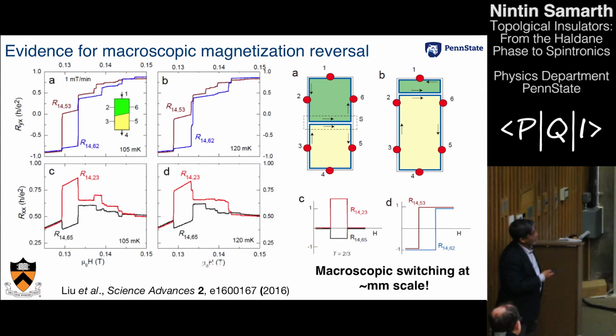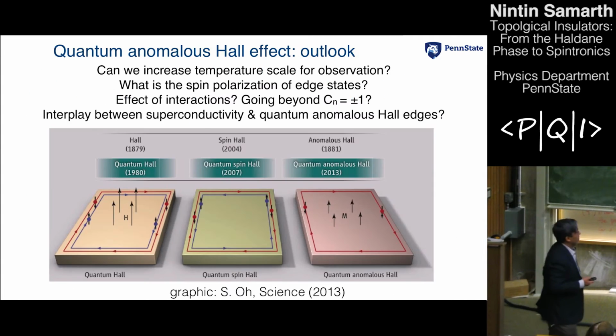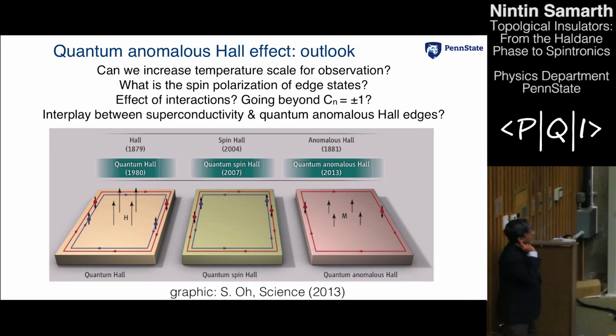So indeed, if we assume a simple model like this, not of uncorrelated switching of little magnetic bubbles, but rather a macroscopic change of the magnetization across this large millimeter scale sample with a single domain wall, or at least some simple structured domain wall, sweeping by, we can in fact reproduce this kind of phenomena that we see in experiments. In other words, Rxx jumps up and down for opposite contacts, and Rxy has a lag in the field at which the Rxy switches. Now, again, as I said, it's just experimentalists trying to interpret the data without much rigor at this point. So what is the outlook for this quantum anomalous Hall effect, or the Haldane phase?